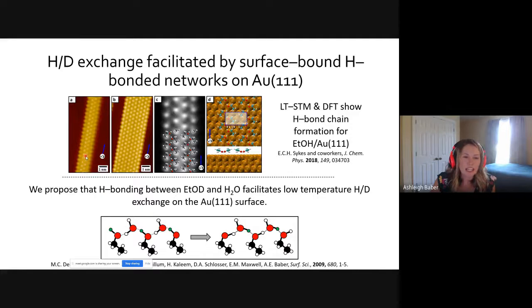So here we're looking at ethanol on a gold 111 surface, and you can see the hydrogen bonded network where all of those ethanol carbon chains are aligned, maximizing those van der Waals interactions between the molecules. But we're kind of expecting, okay, within these hydrogen bonded networks, if water works its way into those and then is able to go through a Grotthuss-like mechanism where you basically can have protons working their way along water wires, that's common in biochemistry, then you can imagine where this could happen between molecular species on an inert gold surface.